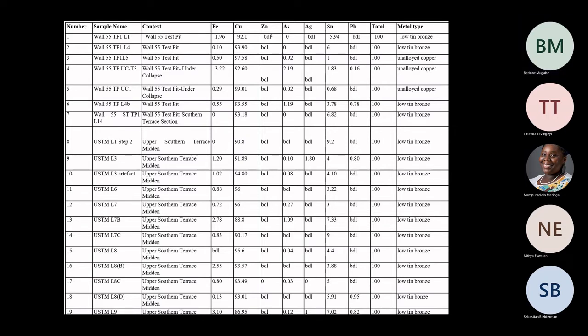Thank you. So what we see here is just a table to give you an overview of the characterization or the composition of most of the metals. I was talking of evidence of low tin bronzes or bronze, evidence of unalloyed copper. So what we see here are the results from SEM, where we see evidence of, let's say, for artifact number one, which is from Wall 55 Test Pit 1, Level 1.